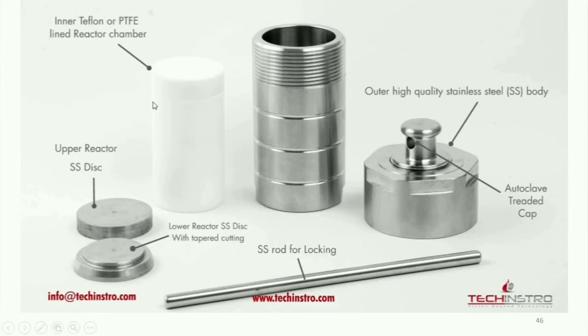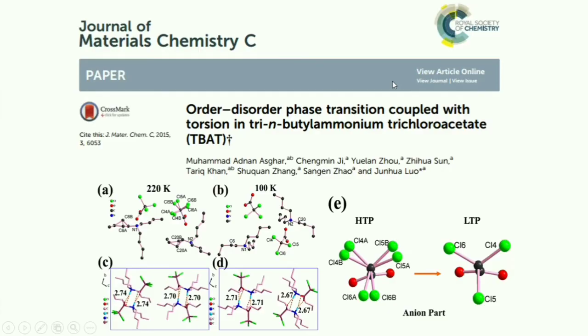This mixture of solution is transferred to the Teflon, and this Teflon is subsequently inserted in the stainless steel container, and then it is sealed properly and put into a heating oven at about 120 degrees Celsius for 7 days. After 7 days of slow cooling, the authors received very nice needle-shaped crystals of this tri-N-butyl ammonium trichloroacetate.